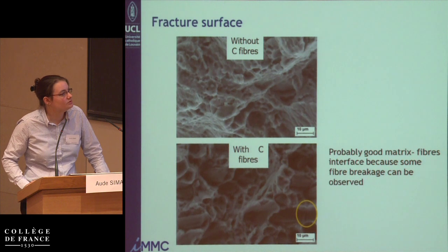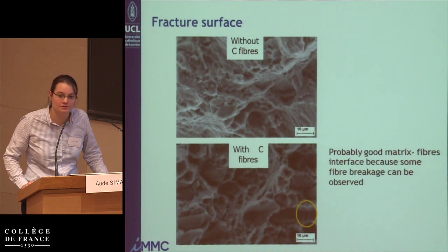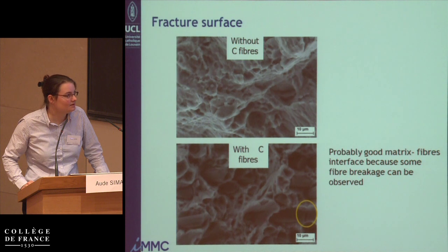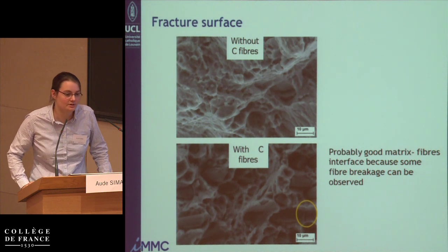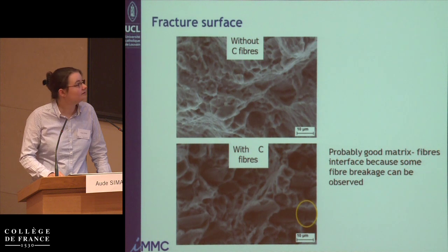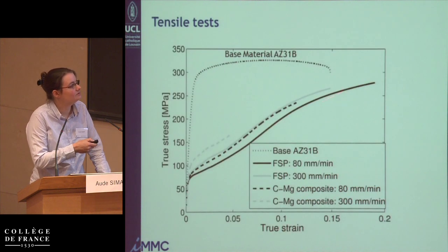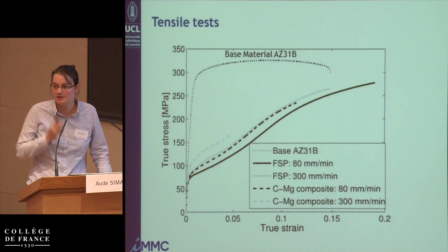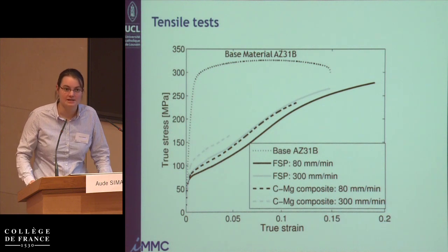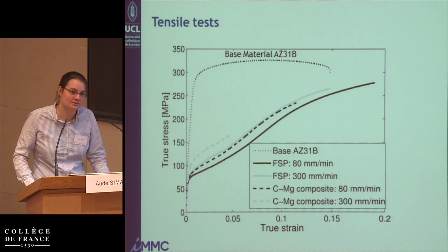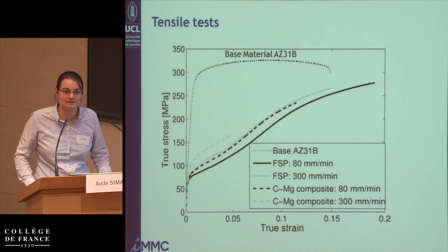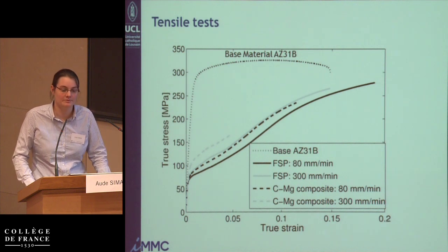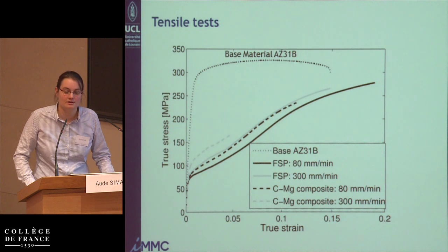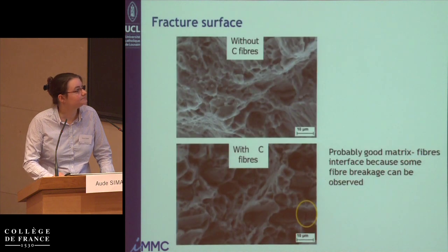Now, this is just to show you again that fracture occurs on the carbon fibers, and so the ductility of the material. If I go back to this slide, well, you see that the ductility of the material is lower when you have the carbon fibers. But yes, well, we are talking about a metal matrix composite, and composites are definitely less ductile than the base materials due to the preferential fracture or decohesion at the interface of the reinforcement.